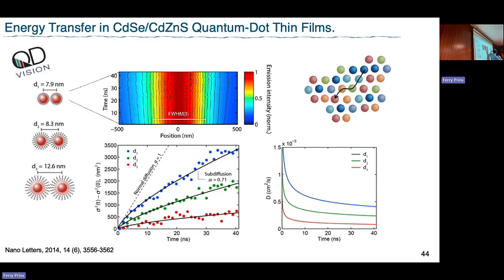As I turn on my communication between the particles, they start moving around. They prefer to move downhill, so when I'm beginning at a blue one, the probability is higher to move to lower energy sites than the transfer between high energy sites and high energy sites. So as time goes by, if I have movement of particles, they're going to go towards the low end of the energy density. Once you reach this point, it cannot give up its exciton anymore because everything is energetically uphill.